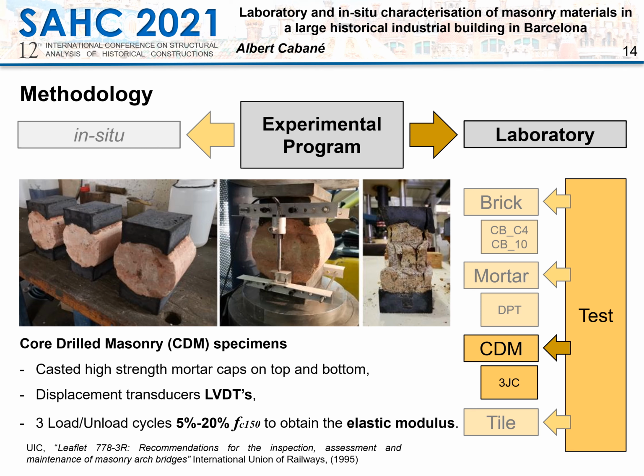The first stage was oriented to study the elastic behavior of the masonry and consisted in the application of three loading and unloading cycles. The second stage of the test was aimed to characterize the compressive strength of masonry, testing the cylinders under compression until the maximum load was reached.